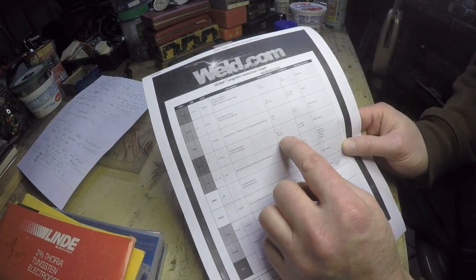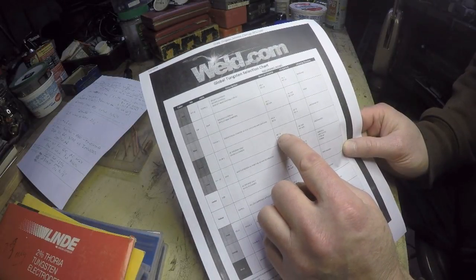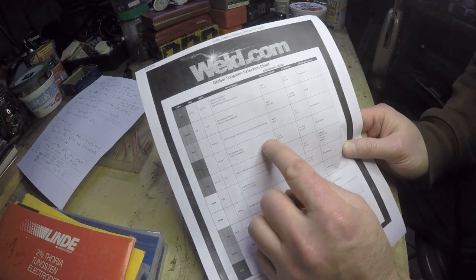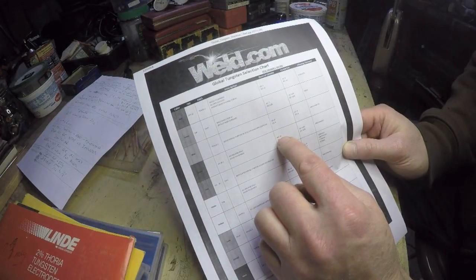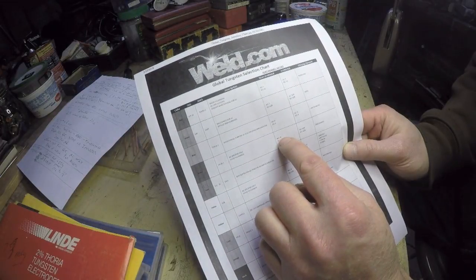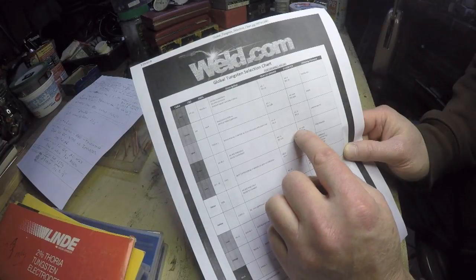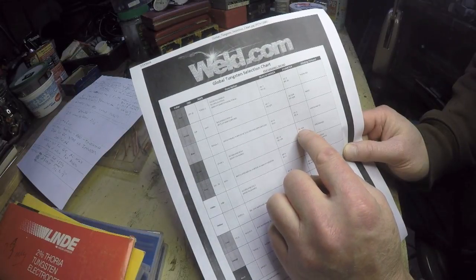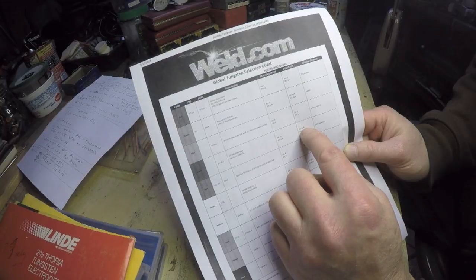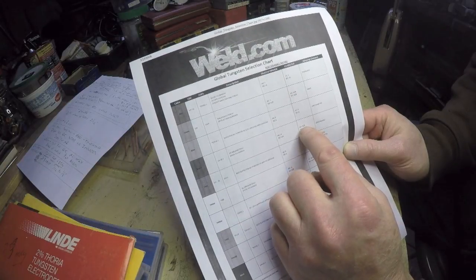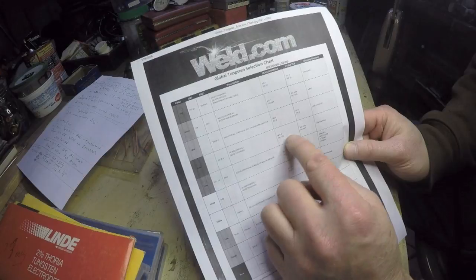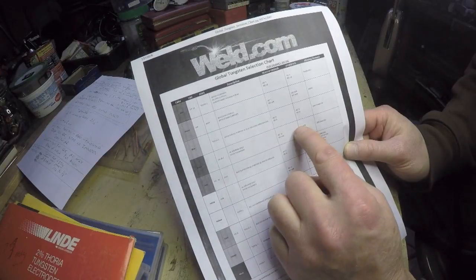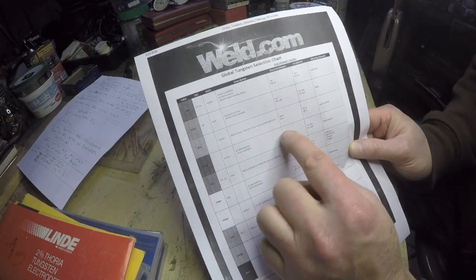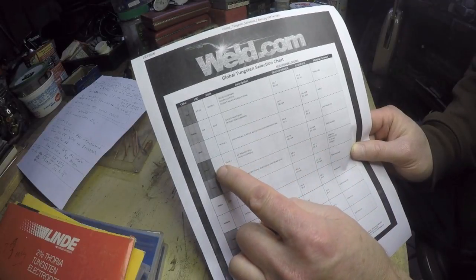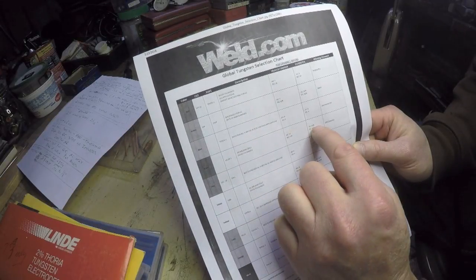But then when we come over here, we'll notice that they give it a 10 out of 10 for AC welding. So this is a very good tungsten for AC welding on a transformer machine. But when we come over to the inverter, look what they say: NR, not recommended. So they actually don't recommend it. And of course, it's no good on DC for either machine because it's for AC only, right? So if you get an older transformer machine, sure, great for aluminum. If you get a modern inverter, you don't want them.